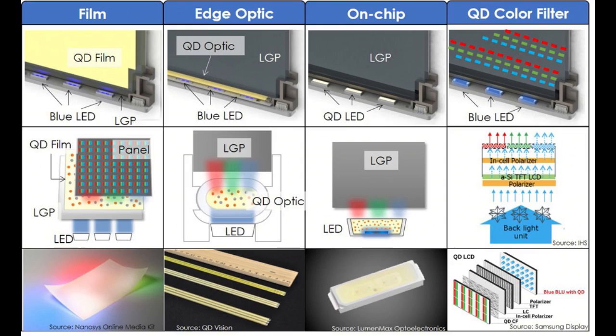So in other words, blue LEDs emit blue light. They pass through this film that's embedded with quantum dots. The quantum dots absorb some of that blue light, but not all of it. Some of it just passes right through the film. The quantum dots, meanwhile, absorb some blue light and they emit red and green randomly over the entire surface of the film. And those red and green emissions combine with the blue that doesn't get absorbed by quantum dots. And red, green, and blue, as we know, makes white. And all they're doing is making white light, really.